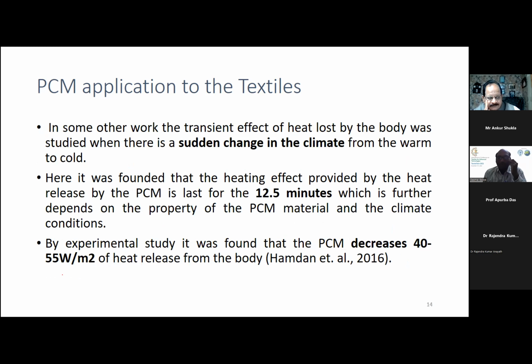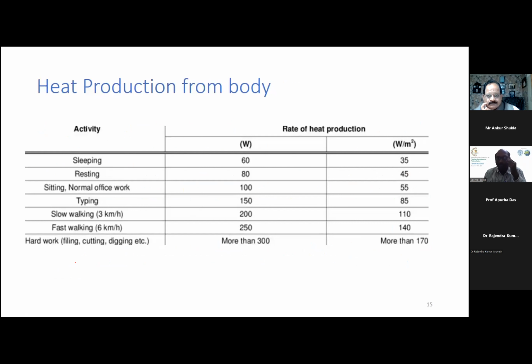Like in some of the earlier work, of 12 minutes, by keeping pockets like ice packs and all, 40 to 55 watts per meter square is achievable. But here with the coating, we were able to do it. So this is the general heat produced from the body. This shows how much, in watts per meter square, the heat production is during sleeping, resting, sitting, typing, slow walking and fast walking, the rate of heat production.